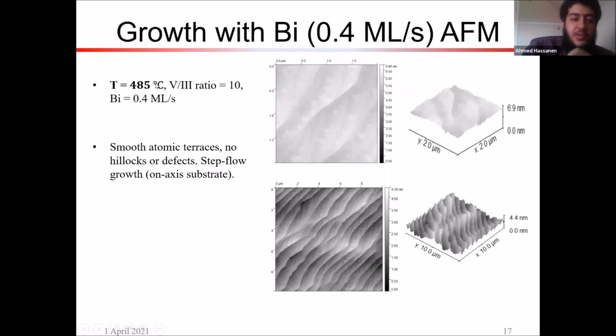And so we started using a higher temperature. So we used 485 Celsius, then with bismuth 0.4, again, just homoepitaxy of gallium arsenide. And what we got was these quite smooth surfaces. If you look at the AFM, you can see the beginning of these smooth atomic terraces, and you can also see very similar shades. You can see it's quite smooth. Also for here, this is just a zoomed out version of the AFM. You can see how we get these very smooth step flow growth.